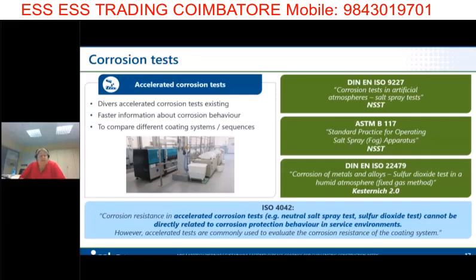But here I would like to mention a comment out of the ISO 4042, which gives the hint that these accelerated corrosion tests, which you can use, you cannot directly relate to the lifetime of your part. Meaning something which survives this and that many hours in NSST, you cannot directly correlate that it will survive, for example, 5 years, 10 years, 20 years in a real-life application.